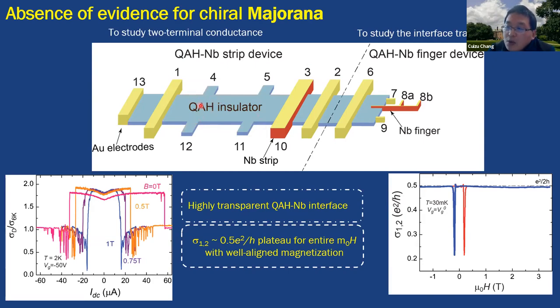If this is a quantum anomalous Hall insulator, and you put an S-wave superconductor here, and you take the two-terminal measurement, a very simple electrical transport measurement, you could get evidence for the chiral Majorana. It forms the chiral topological superconductivity. And the right part is what we call the quantum anomalous Hall and niobium finger device. Using this finger device, we could perform the Andreev reflection measurement. And from this measurement, we can check the transparency between the quantum anomalous Hall and the superconducting niobium film. We are using the Andreev reflection to check the transparency.